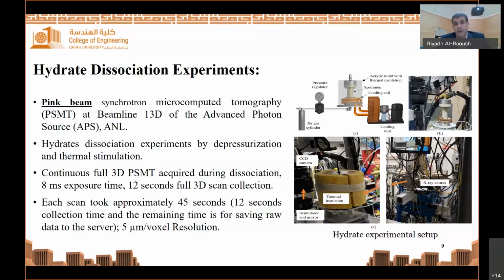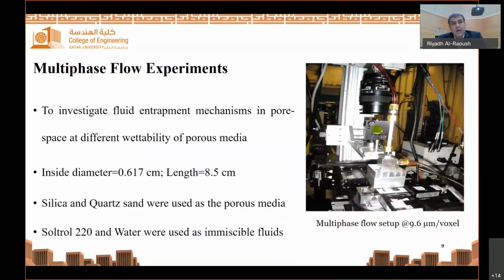This was necessary for our work because the X-ray needs to penetrate the thermal insulation that we have in our sample and the high pressure cell that we used for this setup. The scanning time was about 12 seconds, and the experiments were run for more than 4 hours for hydrate formation and another 4 hours for hydrate dissociation.